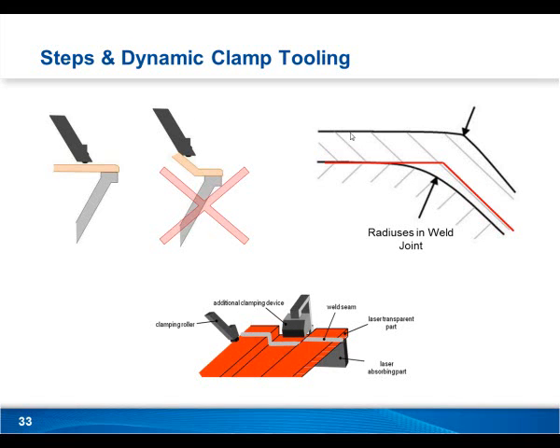Also, you see joints like this. We typically try to smooth out the inner curve of the joint. So where you see the red line here, instead we'll suggest that you do a more radiused interface between the two parts. And in this way, we're going to ensure that we distribute the clamp force evenly. So as that roller arm travels along here and then hits this step, we can ensure that all of the clamp force throughout that whole process is going to be distributed evenly throughout this entire interface, and you're not going to see gaps being created with different angles of pressure.